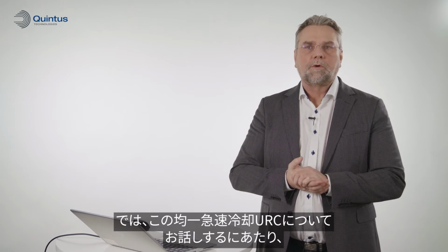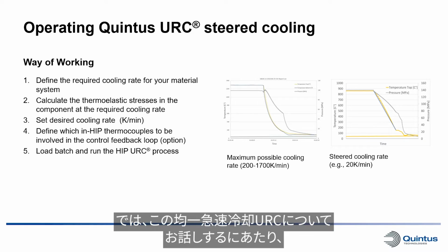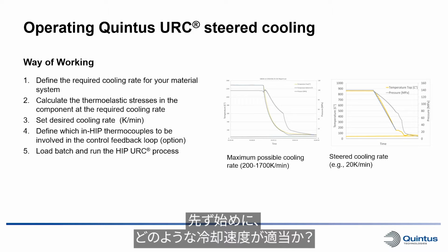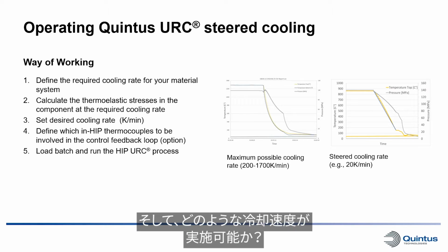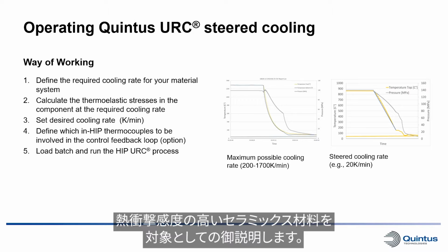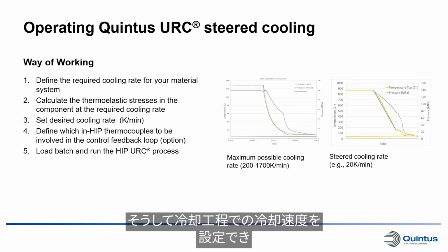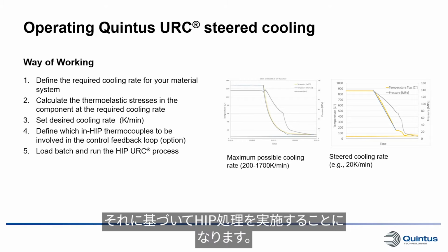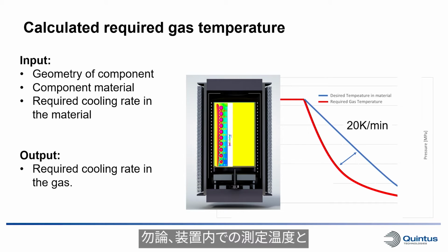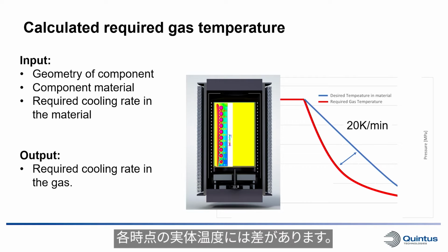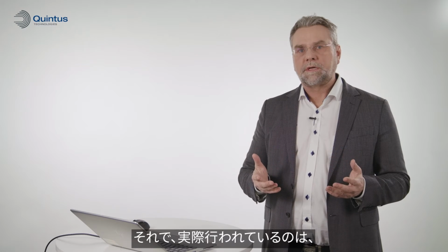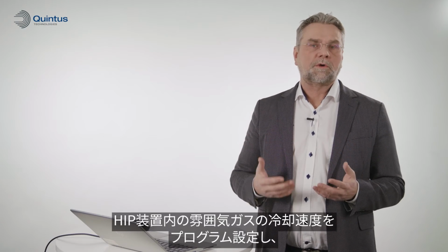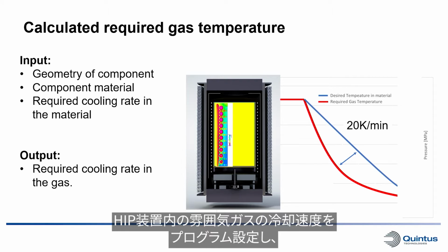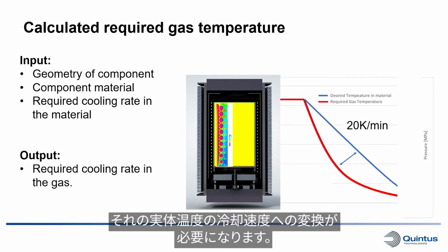Okay, so how do we go about using this uniform rapid cooling? Well, we need to start off by defining what cooling rate we would like to have, and also what cooling rate we can have when it comes to thermal shock sensitive ceramics. Then we can set this cooling rate in the cooling segment of the HIP cycle and run the cycle accordingly. Of course, there's a difference between the temperature we are reading inside the system and the temperature the components have at any given time. So what we are actually doing is programming the cooling rate the gas inside the HIP system should have, and we need to transfer that to the cooling rate in the components.